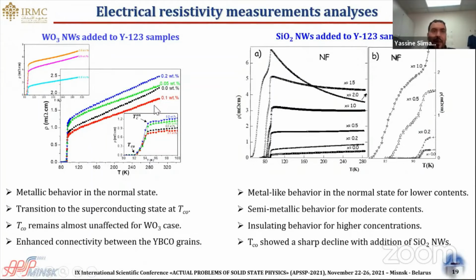It is evident here that the different tungsten oxide nanomaterials added to YBCO samples displayed a metallic behavior in the normal state, followed by transition to the superconducting state at a temperature noted here as Tco. The addition of small amounts leads to a decrease in resistivity in the normal state, and does not affect the critical transition temperature. Sometimes, in some cases, we can find a slight increase in the critical transition temperature. This is mostly attributed to the enhanced connectivity between the YBCO grains, as revealed before via morphological observation.